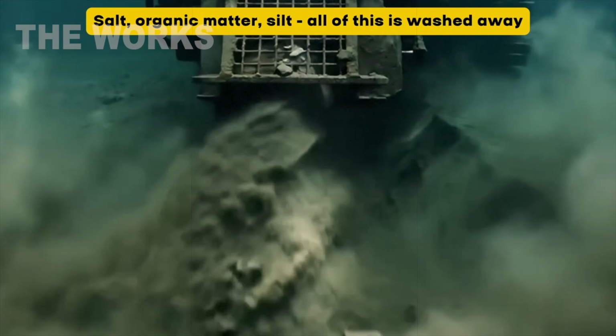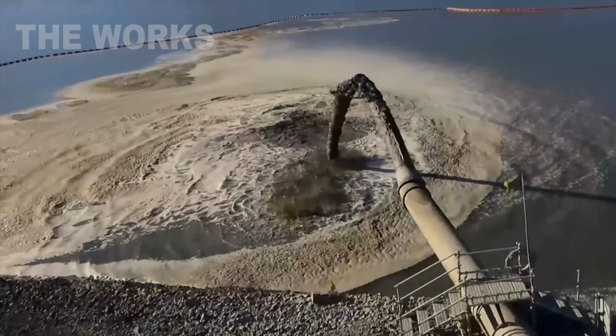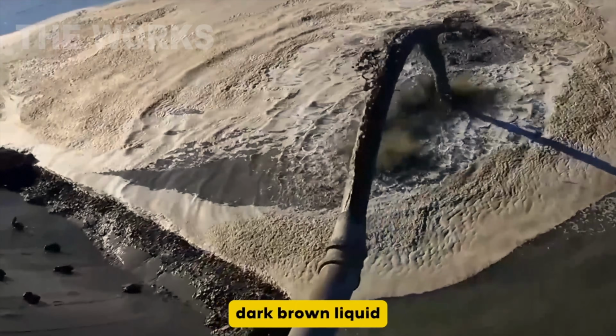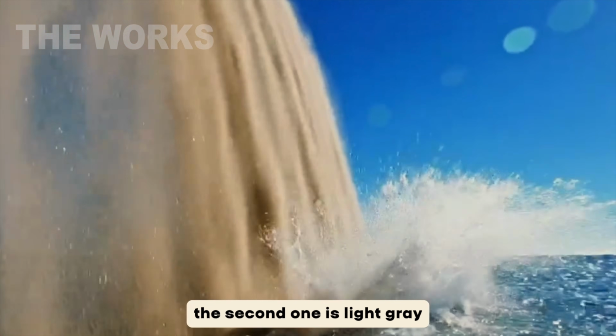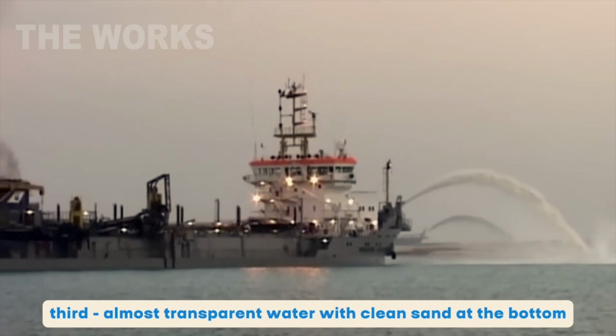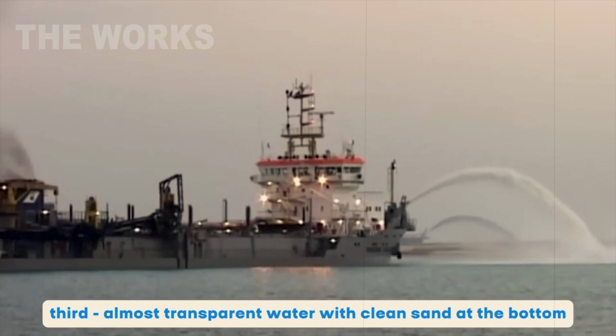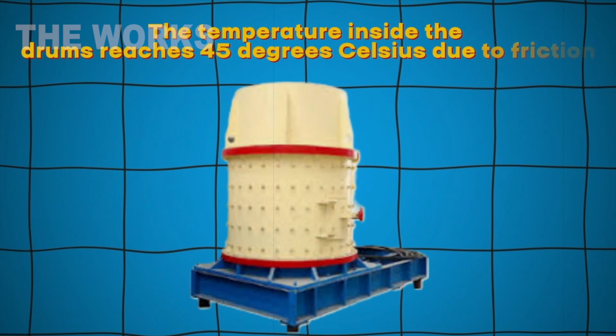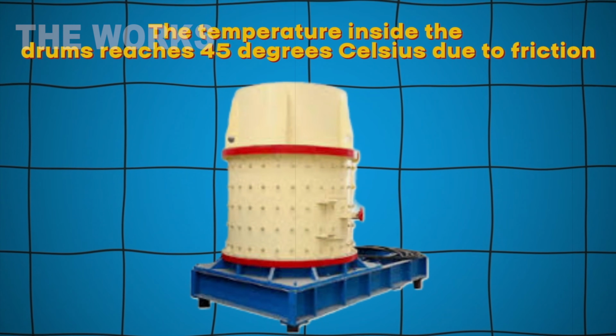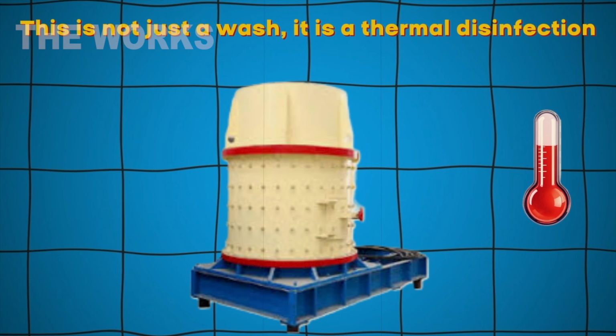I watch as dark brown sludge comes out of the first drum, light gray from the second, and from the third, nearly clear water with clean sand at the bottom. The temperature inside the drums hits 113 degrees Fahrenheit because of friction. This isn't just washing, it's thermal disinfection. Any organic residue, bacteria, algae, they all die in this hot whirlpool.